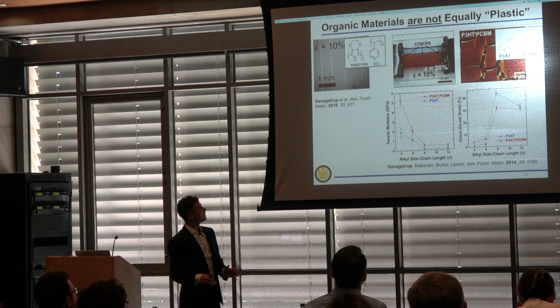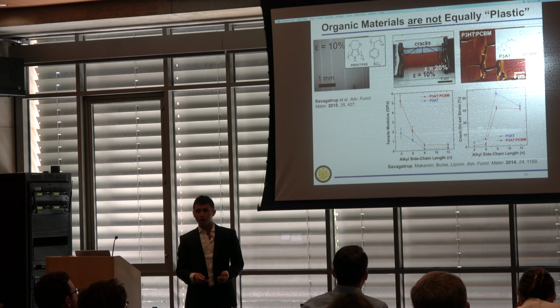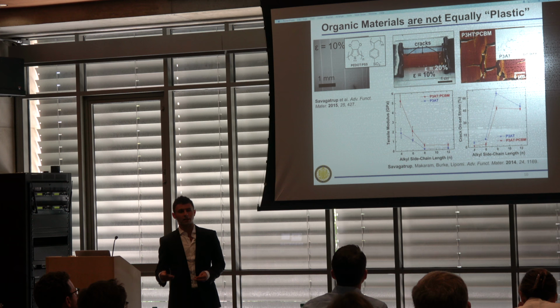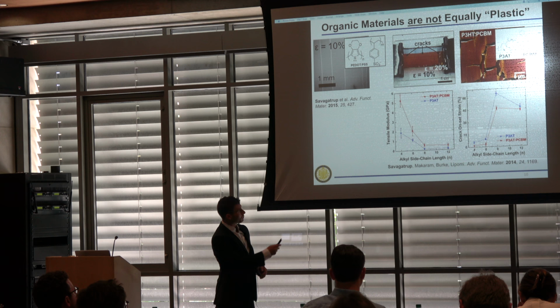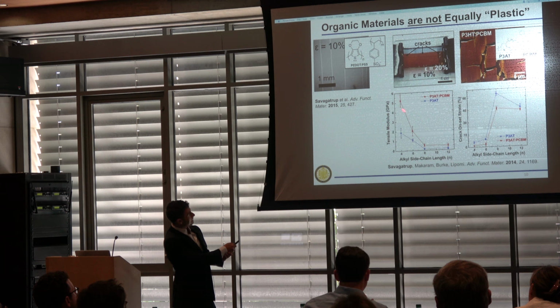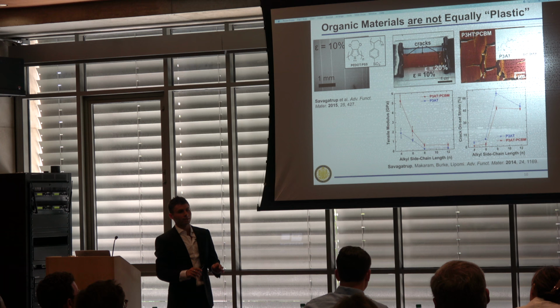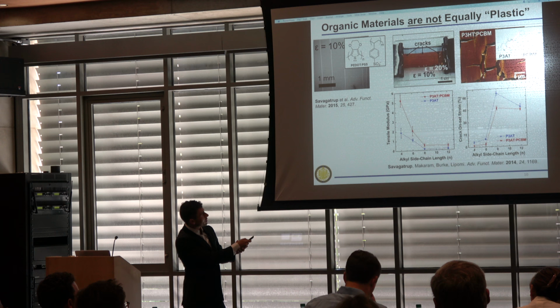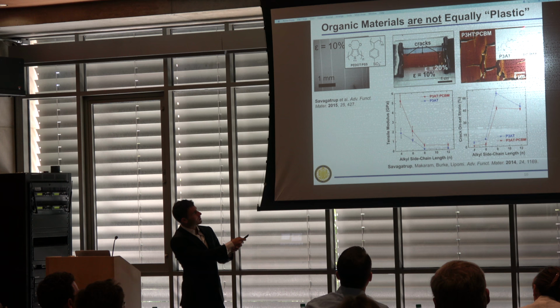When we started in 2012, all of the literature actually stated P3AT:PCBM, organic photovoltaics, are flexible and stretchable. So some of our first studies aimed to dispel this and figure out why they aren't and how to make them more mechanically compliant. One of the first studies conducted by our group, spearheaded by Suchol as I mentioned, was just changing one molecular parameter and seeing how this affects the mechanical properties of the bulk and of thin films. That is changing the length of this alkyl side chain from 4 to 10, the carbon chain sticking off the thiophene.